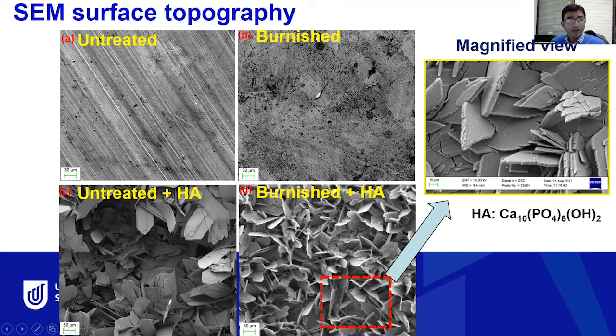We can see that the burnished surface is fairly smooth because we modified the surface, removing a lot of the peaks and valleys. And then after we deposit the HA coating on the untreated and the burnished, we can see a very platelet-like crystal structure of the HA coating deposited onto both surfaces. However, when you deposit the HA coating on the burnished surface, we can see a very smooth, very compact, and kind of dense HA coating structure being deposited.